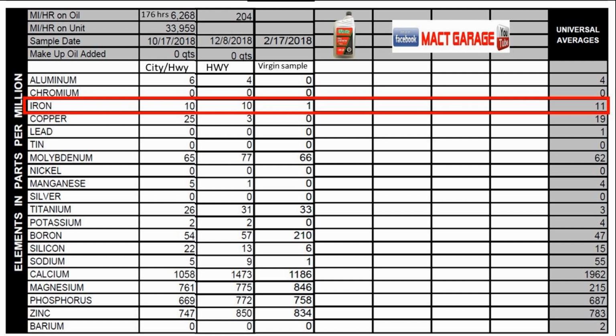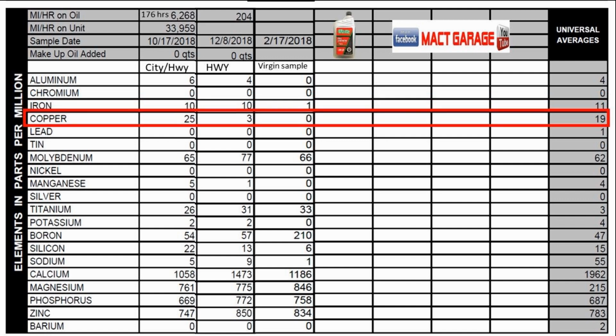With the virgin sample with just 1, and the universal average for used samples is 11. So both edges are under the universal used sample testing. Copper: the city highway edge with 34,000 miles on it came in at 25 parts per million, which is a tad over the used analysis of 19. But my edge came in at 3 parts per million for the copper, so she's running sweet and no problems.